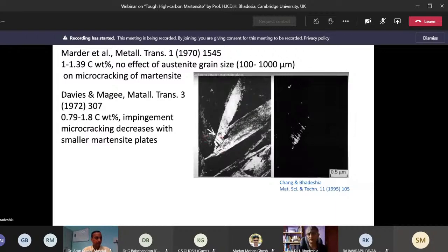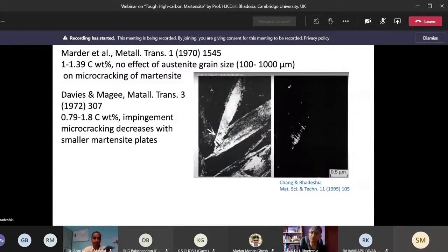Many of the cracks are caused by the collision of martensite plates, which have started from different locations, and you accumulate damage at the contact point. Here you can see mechanical twinning induced in this plate as a consequence of collision with this plate. And if this martensite was brittle, then these would actually be microscopic cracks. So if you have a crystallography in which the plates of martensite make a high angle with respect to each other, so these are different crystallographic variants, then you are more likely to get cracking.